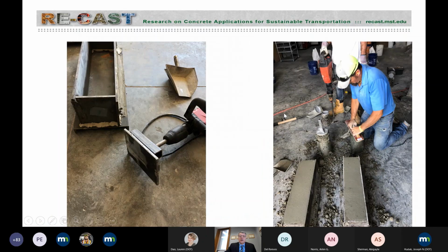Here also is the sampling of the prism, the 6 by 6 inch prisms. Again, we consolidate them using this vibratory plate, and then going layer by layer across and finishing it until we ensure that we have good density. Now in the lab, when we were doing this, we tried it on purpose to have different operators during the consolidation, and you get quite a bit of variability according to the operator.